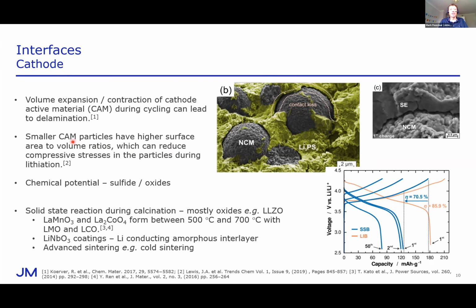But we do know that smaller active material particles can have different stress properties, and so the effects are lessened with the right particle size. And of course, matching the thermal or elastic properties of your electrolytes with your active materials would also be a benefit. And not all active materials show this volume expansion. NCM is a common one, and it's good in many ways, but things like disordered rock salts and perhaps some spinel materials behave differently, and so the problems are different and lessened. Of course, there are also chemical reactions that can occur between sulfides and oxides spontaneously, just chalcogenide exchange reactions forming mixed chalcogenide phases at the interface with detrimental results to the electrochemistry, and that leads to space charge effects as well.